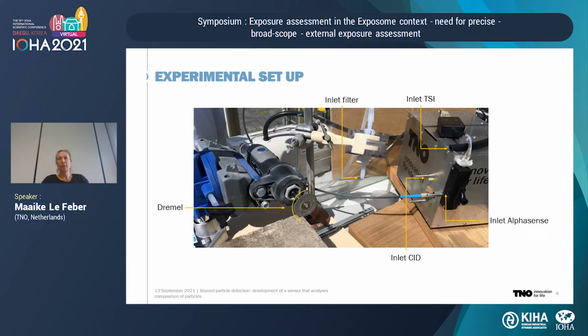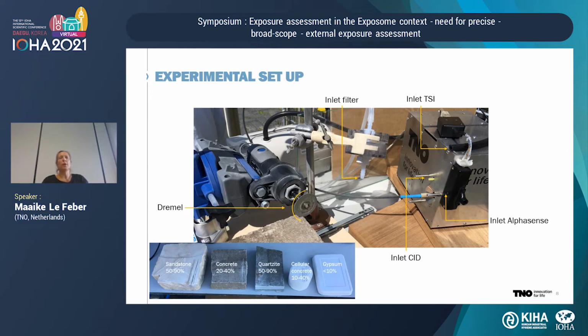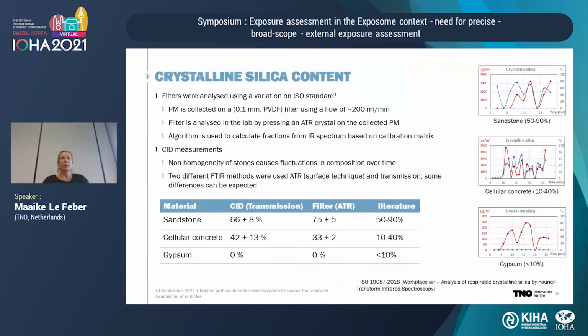We also used a TSI as a high-end particle counter. We used our own CID in parallel with an AlphaSense particle counter. And we used this experimental setup on 5 different materials, differing in the amount of crystalline silica that was in the material. So the percentages here refer to the content of crystalline silica. So the filters were taken and were analyzed after the experiment using a variation on the ISO standard for workplace air assessment.